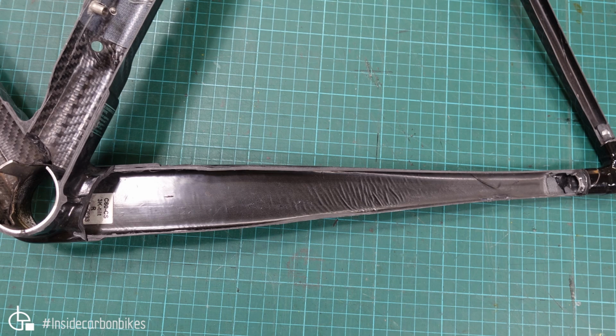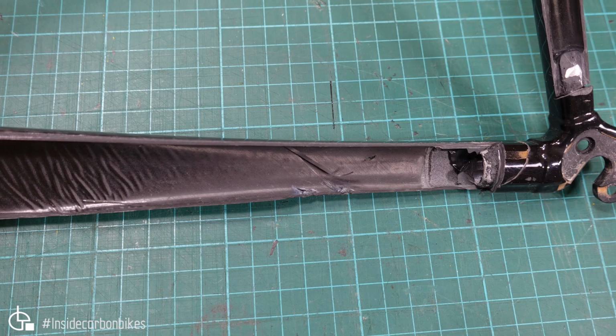And overall on the chainstay, a little bit resin rich, you can see these lines through here where there's some resin pooling. Pretty minimal though, really. It coincides with where the bag necks down, so it goes from a larger section through here, and then parallel sided again, but through that transition, that's where you're getting this problem. So just probably a little bit of wrinkling in the bag. That's not really a big deal. We do see a bit of delamination through here, which we'll have a closer look at.